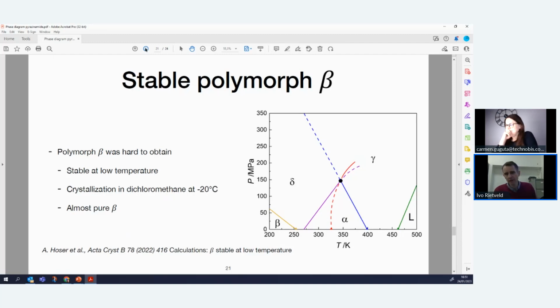So seeing this, and also all the frustrations that we had with getting a nice beta crystal, we did one final experiment, and that was simply recrystallization of pyrazinamide at low temperature, at -20, in this case in dichloromethane. And we had indeed almost pure beta. There was a little bit of delta in there. It was really a tiny little bit, and we don't know if that is just due to the fact that we did our measurements at room temperature, so we had to bring up the temperature of our pure beta, or that maybe we should have done the crystallization at a bit of a lower temperature. But basically, the sample was pure beta. So that showed that it was much easier to obtain beta at these very low temperatures.